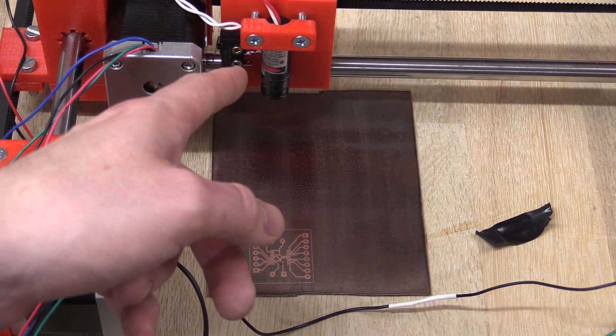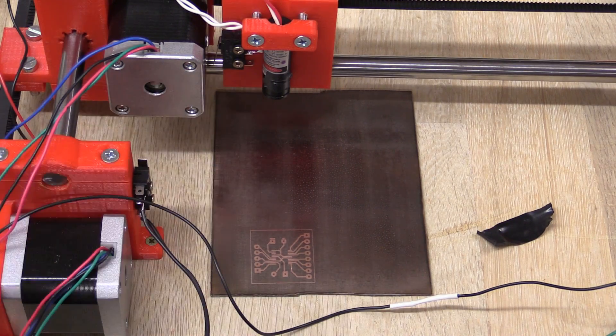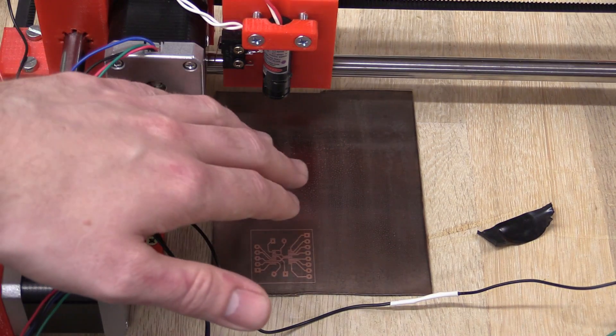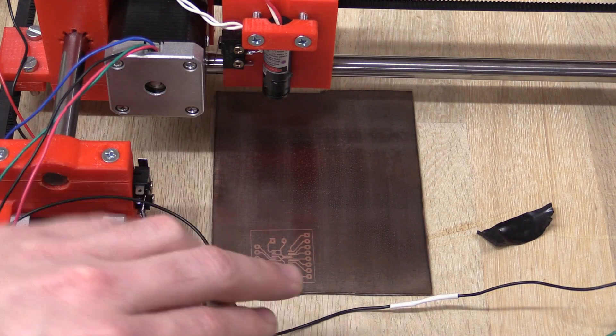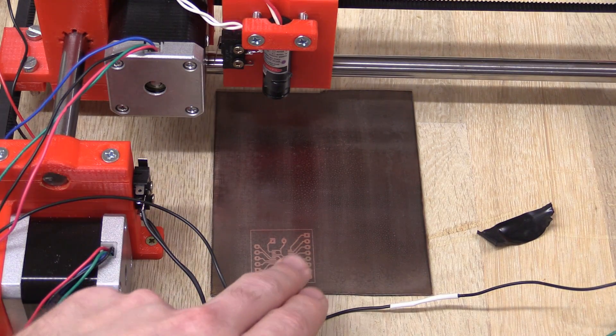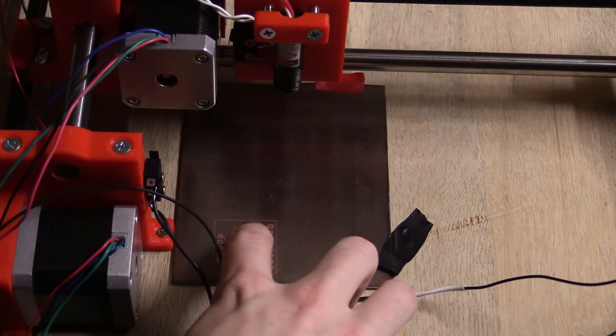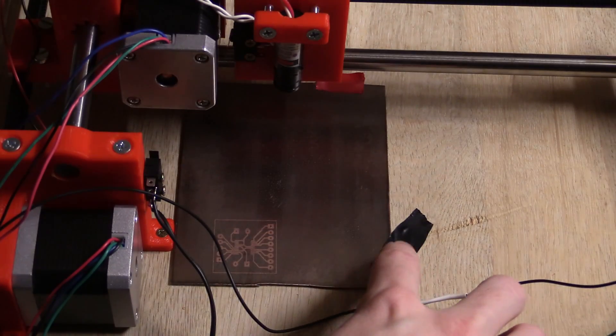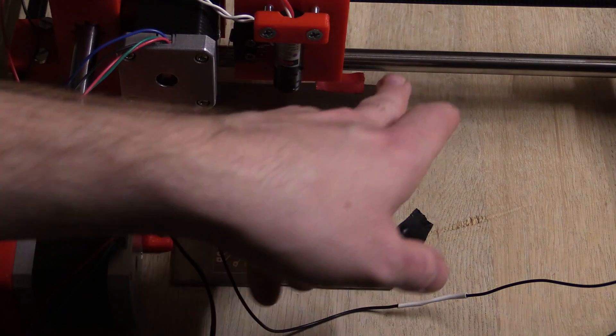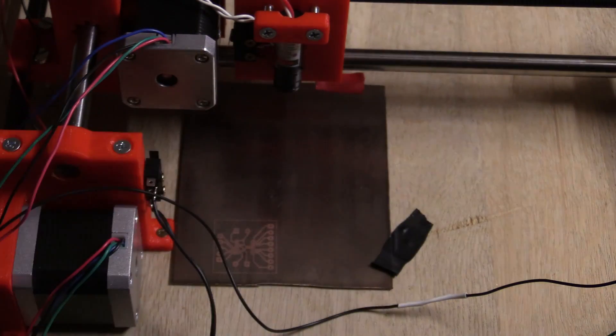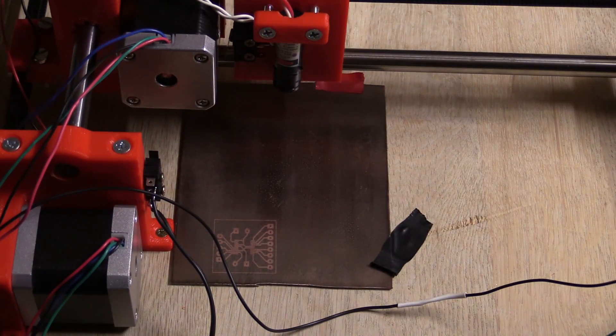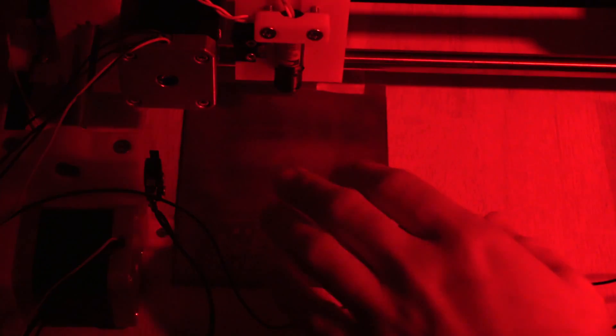I will try and speed it up a little bit and see if it will still expose correctly, and maybe it will remove some of the overexposed traces so the traces get a little bit thinner. Also I can give the laser a little bit more power than it receives right now and still stay within the specifications. It's rated for about 200 milliamps and I'm giving it 150, so I'll try and do another one and then we'll speed it up a little bit and see if it will expose it better.